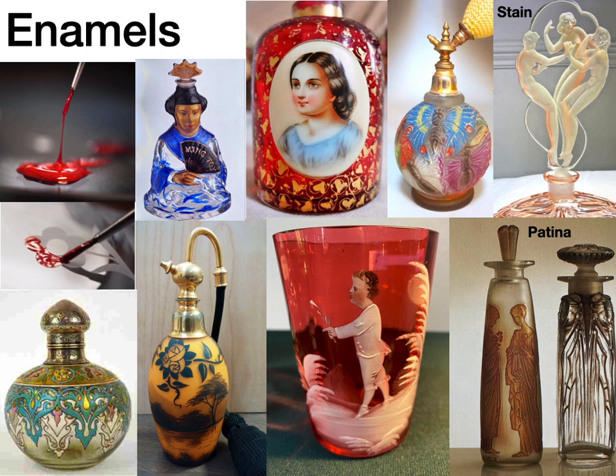Enamel is a finely powdered glass mixed with a fluxing agent and coloring oxides. It must melt and fuse to the glass at a temperature below the slumping temperature of the glass. A stain, as in the top right, is a translucent enamel that's often sprayed on. It's also fired so it won't rub off. Some call it a patina, which I think is just a French name for a stain.